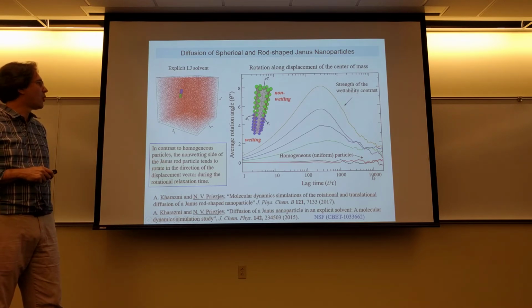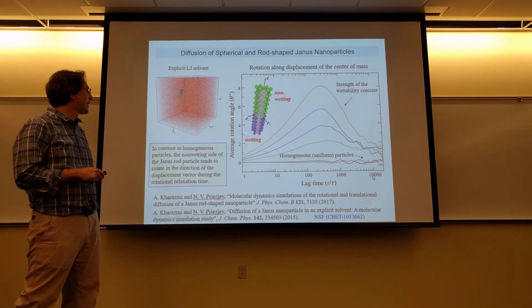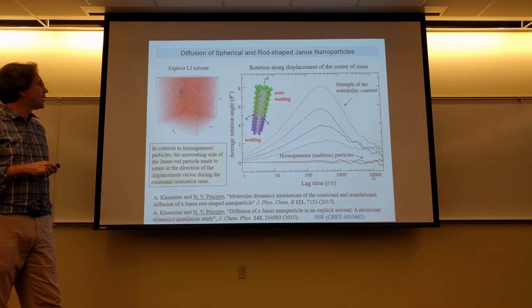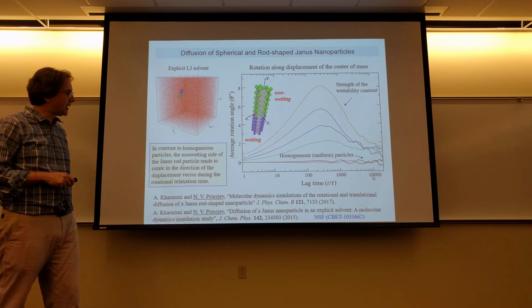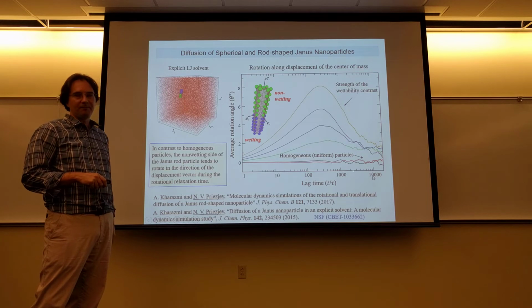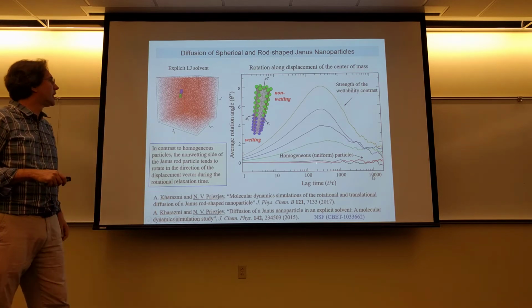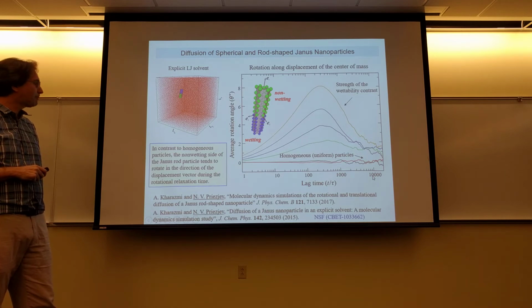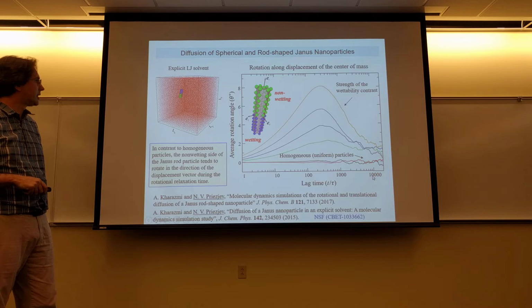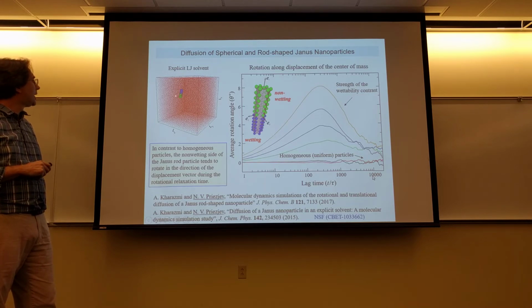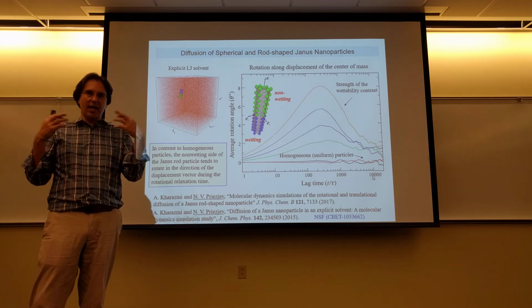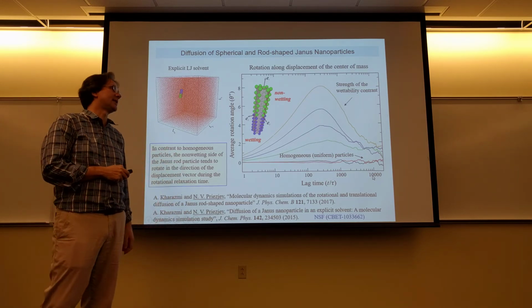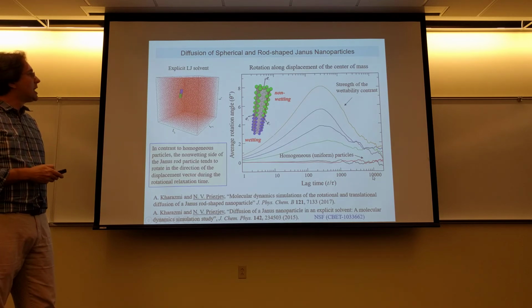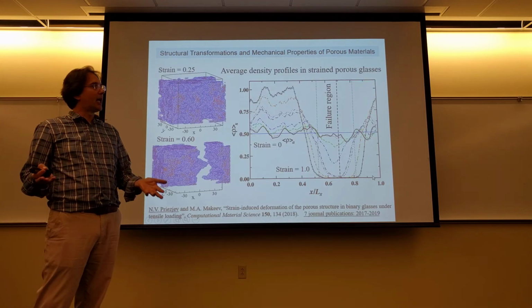This type of motion can be picked up by a special correlation function, which measures this average rotation angle towards displacement on a time scale typical of the orientation of the nanoparticle. This correlation function and many other features we considered in a couple of recent papers. This research is important in elucidating what happens if you have many of such particles and you're studying, say, self-assembly of those.